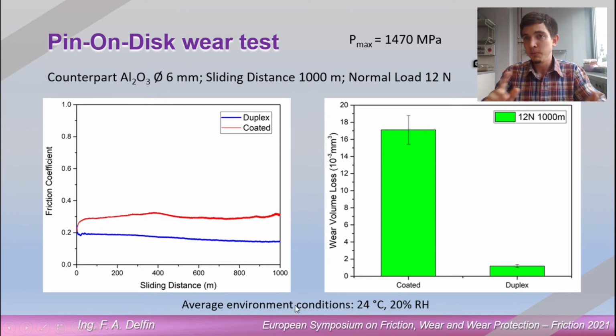So this triggered another test we are doing now with different relative humidities, and we see here that the coated sample has more wear than before, but the duplex sample is still the same. So yeah, we saw more delamination in the coated sample due to the increase to 1.5 gigapascal in the contact pressure. So more delamination, which affects also the friction coefficient.